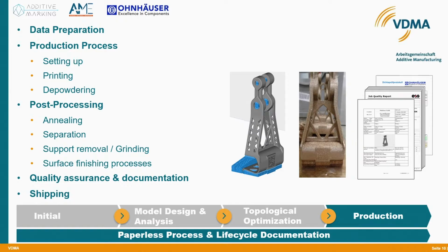Thank you, Mr. Janke, for the transition. Due to the optimized geometry, only a few supports are required for printing this part. The data preparation defines types and positions of the supports. The tasks of the supports have already been explained. Before transferring the build job to the machine, the exposure strategy has to be defined. The machine also has to be set up for a build job. The main tasks are to screw on a new build platform and fill in the titanium powder. After the process conditions have been reached, metal powder is welded layer by layer into parts.